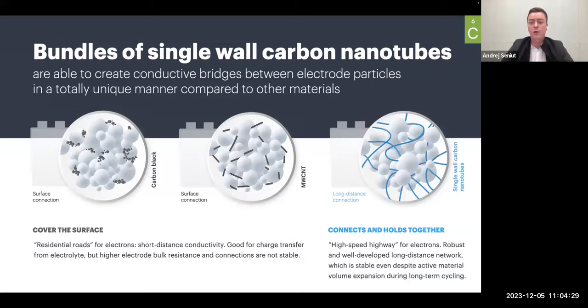battery systems. Why? Because carbon black and multiwall carbon nanotubes are materials which are small in size and quite rigid. The material more covers the surface of active material particles, which you can see here to the left on this slide. And these surface connections create some sort of residential roads for electrons, which promote short distance conductivity. This is good for charge transfer from electrolyte, but requires more conductive material inside to establish connections between the particles, as well as leads to higher bulk electrode resistance, and these connections are not stable.